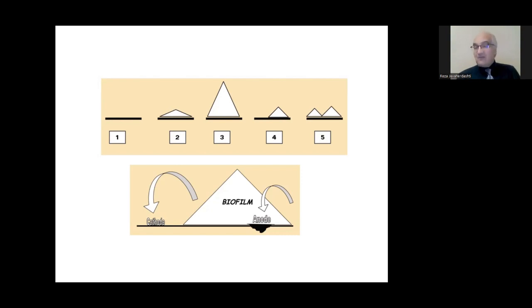But whether or not MIC could be a primary corrosion scenario or a secondary corrosion scenario, my experience tells me that in many cases MIC could be a primary corrosion scenario, enhanced by other corrosion processes already present in the system. So there is always this competition between MIC, like for example, in cases of failure due to hydrostatic testing that I have worked on, we have seen that, for example, the failure has almost always happened on weld zone, on heat affected zone, all right?